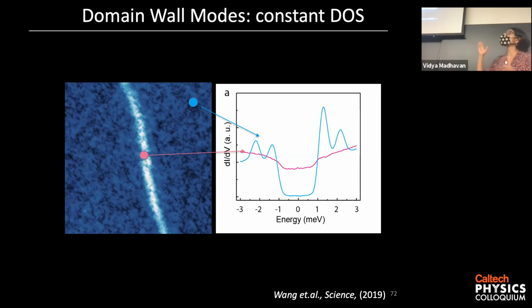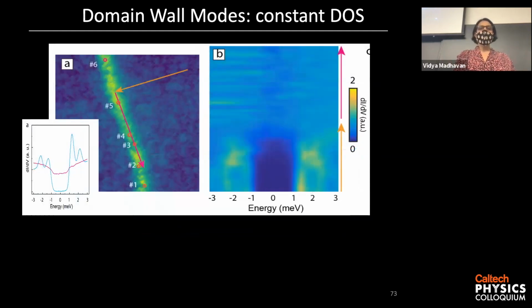So when I first saw this, I was very struck because I've studied a lot of superconductors over the last couple of decades. And usually when we go to a defect and we look at the density of states, either the gap gets smaller or there are sharp peaks inside the superconducting gap. I'd never seen something like this where the density of states is actually uniform inside the gap. So this is just to show that it's true across the domain wall. So as you go across the domain wall, you can see that the density of states, this is a color plot of the density of states. It's basically featureless.